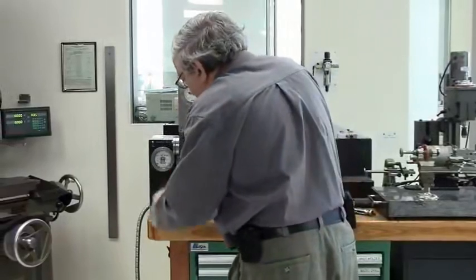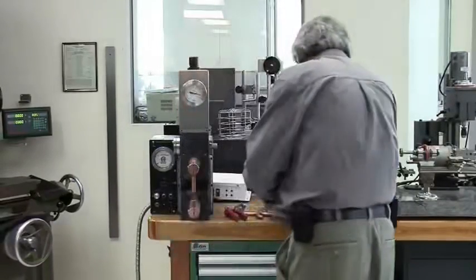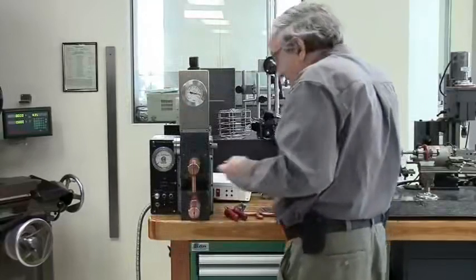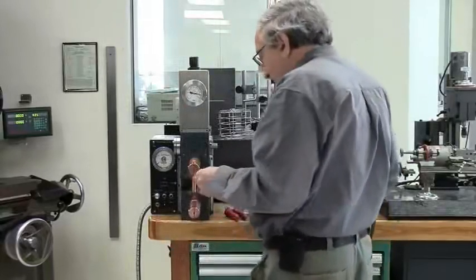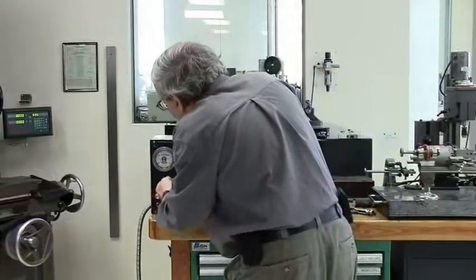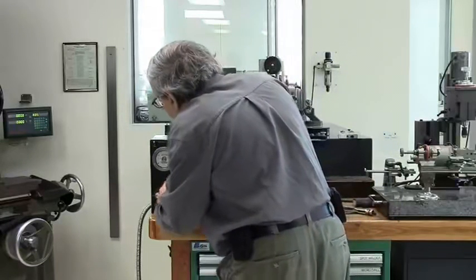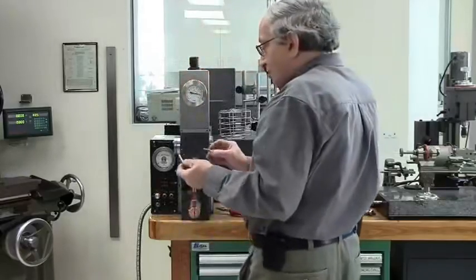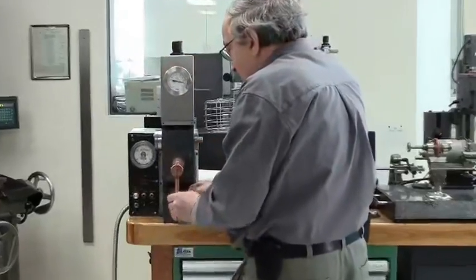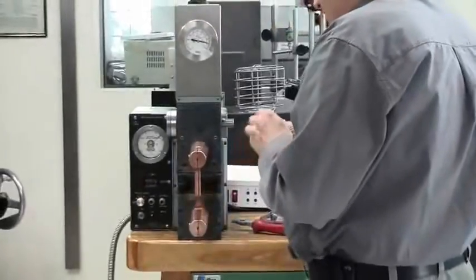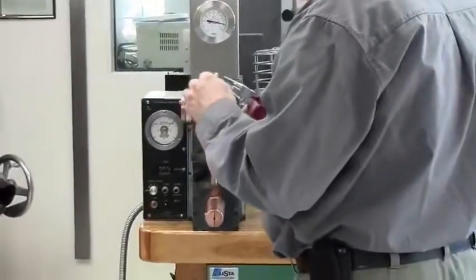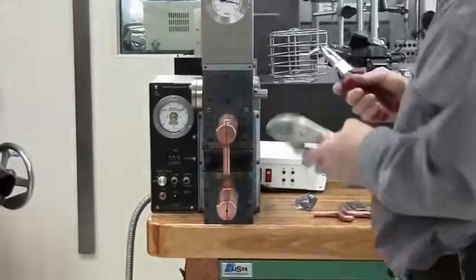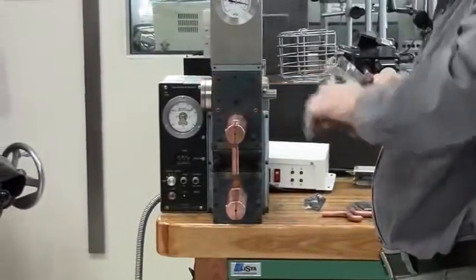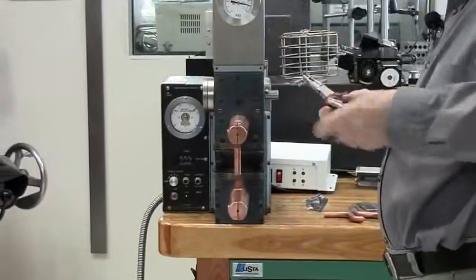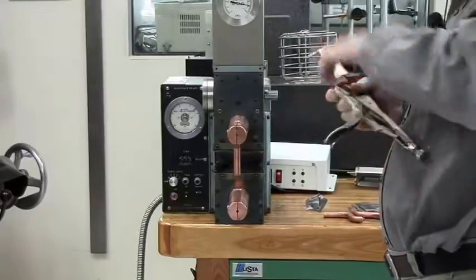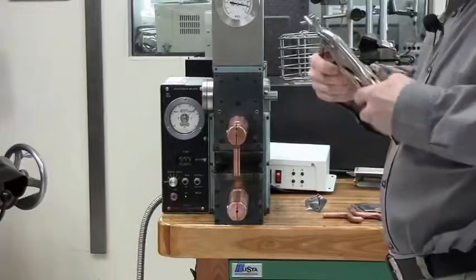So even a 15 kVA unit will easily weld 3/8 rod, and then weld even 1/2-inch rod. For example, even on a low setting of 5, okay, so it's a 1/4-inch rod and a 3/16 rod. It will weld them very nicely together. Maybe that's a bit under welded, but if not, we can increase the setting. Let's see this. And the test is the same. You have to twist the rod, and the weld should not open, the rod should shear. Same test.